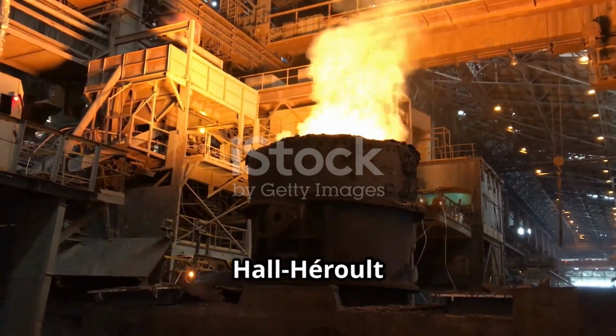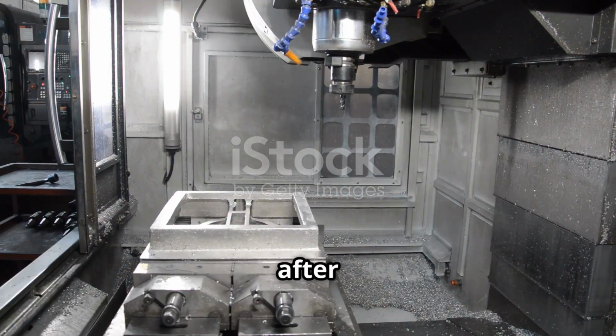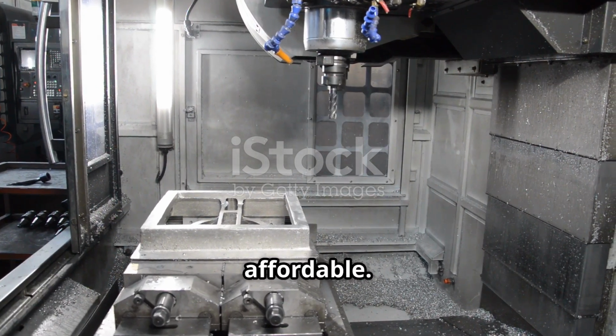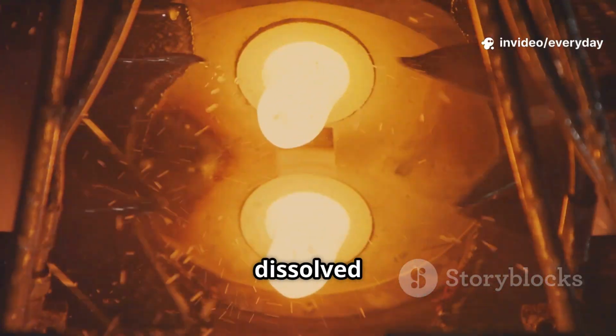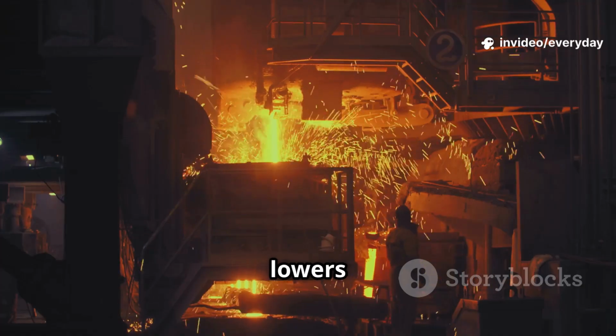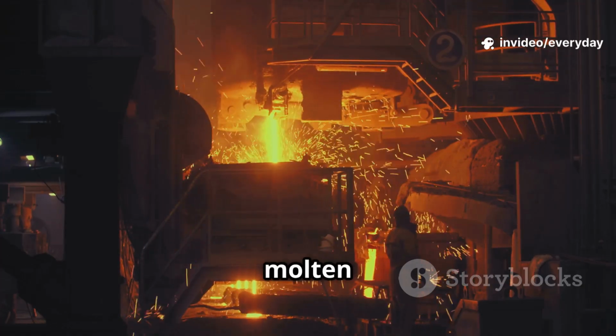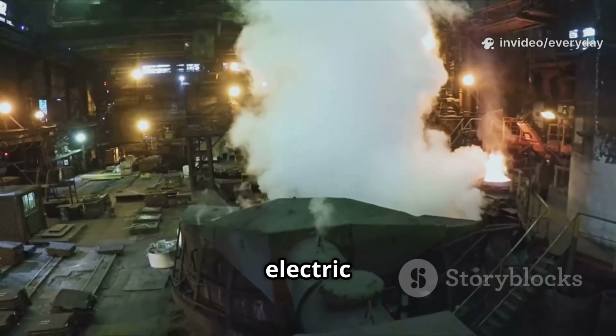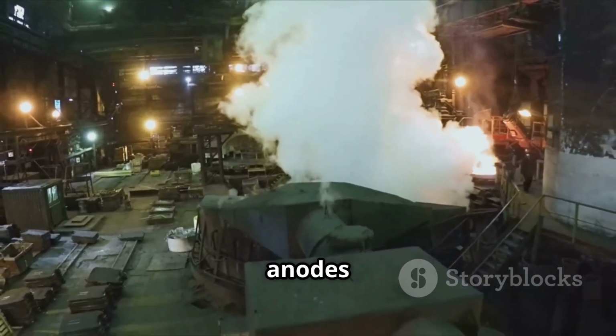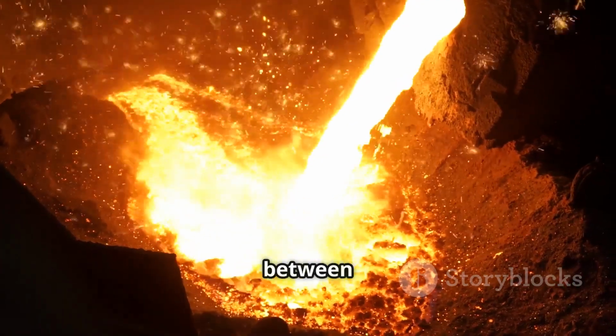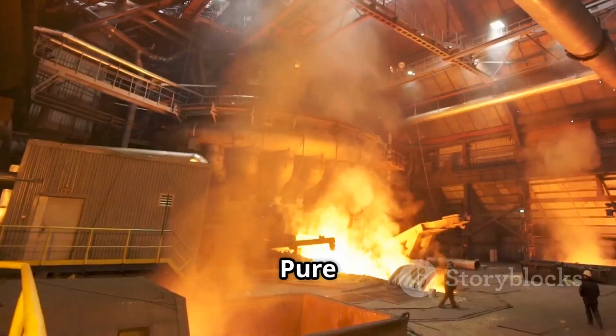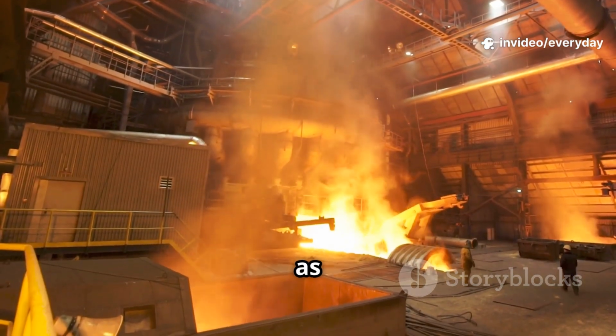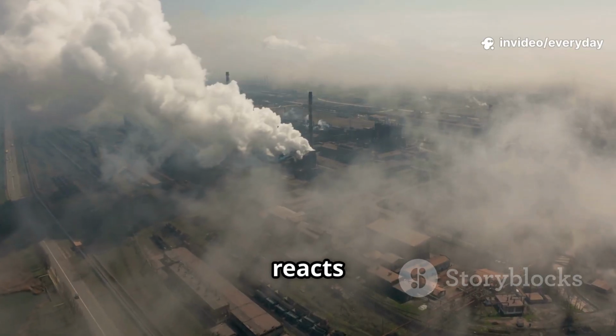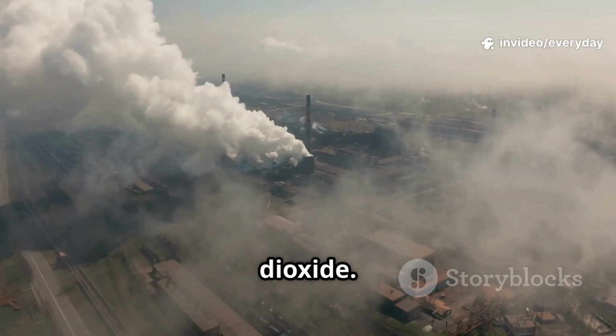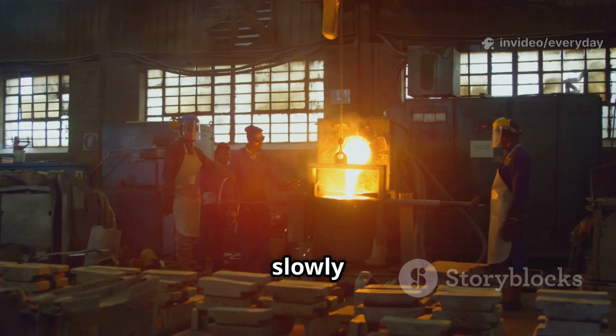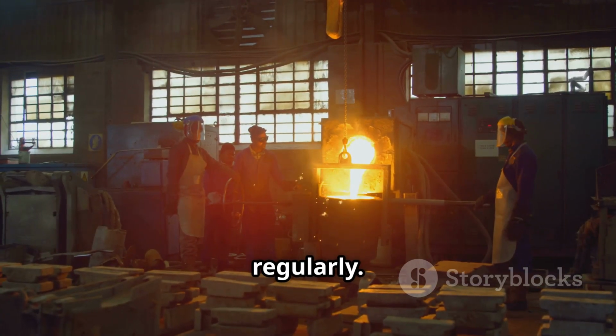At the smelter, the Hall-Héroult process takes over, named after two inventors who made aluminum affordable. Alumina is dissolved in molten cryolite, which lowers the melting point and creates a hot, molten bath. Huge electric currents are passed through carbon anodes into the bath, breaking the bond between aluminum and oxygen. Pure aluminum sinks to the bottom as molten metal, while oxygen reacts with the carbon anodes to form carbon dioxide. The anodes are slowly consumed and must be replaced regularly.